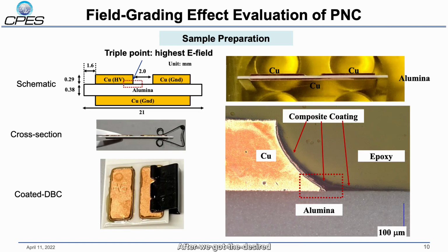After we got the desired electrical properties, it's time to validate this field grading effect on real DBC substrate, which can be used for packaging power module. Here shows a schematic of the test sample. The DBC substrate is patterned with 2 mm gap between the 2 copper pads, and the alumina thickness is selected to be 0.38 mm. Here is the triple point.